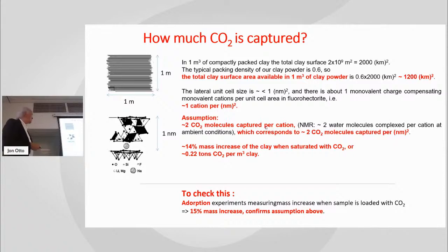And to check this, we did some adsorption experiments, measuring the mass increase when the sample is loaded. We loaded the sample with CO2, got as much as we could into there. And these are some early, the first checks we did, and you see 15% mass increase is what we measure. The estimate was 14%. But now we have improved this.